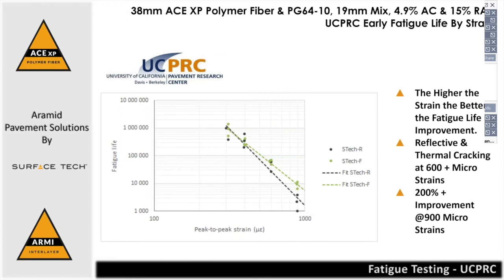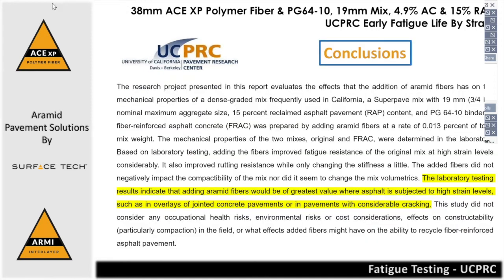I can't make that. But by moving from a steeper line at the black one to a flatter line, it means my end result material becomes less sensitive to movements in the pavement. And that was really important. That's what lit me up to say this could be a good interlayer product. And the good folks out at UCPRC saw the same thing in their testing.